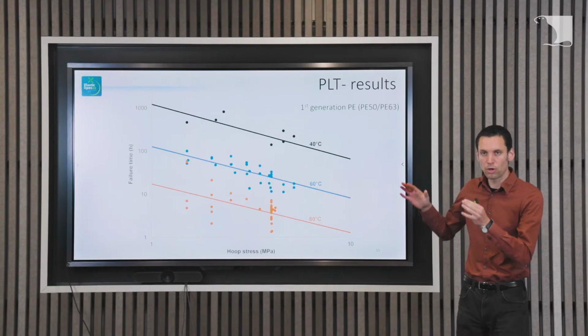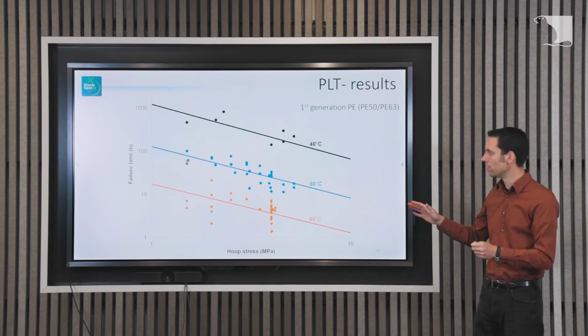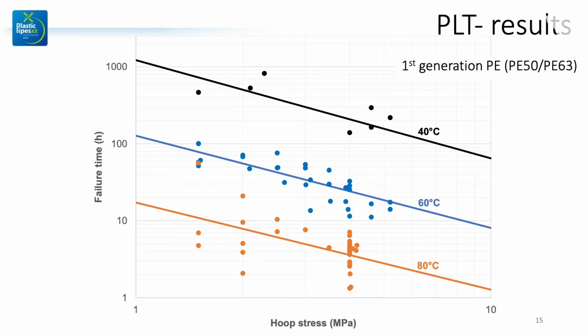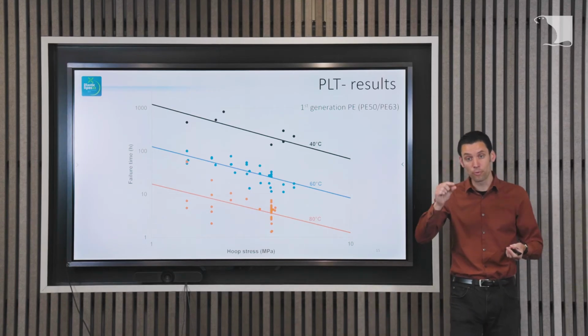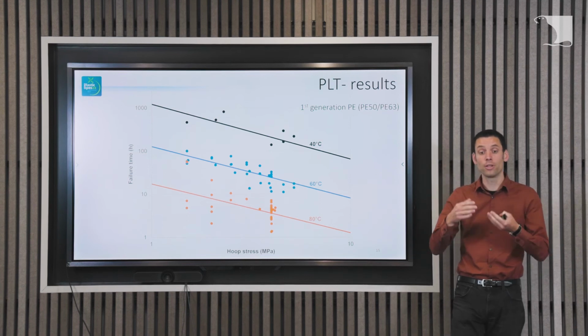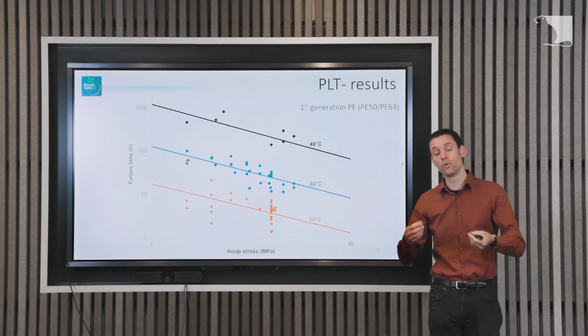We did already quite some tests, especially on the first generation polyethylene that is used in the Netherlands. So that's really the polyethylene pipes that were installed like 50 years ago. We already published it, and these are, well, the latest results. So what do we see here? First of all, on the vertical axis, we see the failure time of these pipes. On the horizontal axis, we see the hoop stress. So the internal pressure actually of those polyethylene pipes, but it's corrected for the wall thickness. Of course, a pipe with a thinner wall will have, under the same pressure, more stress inside the material than a thick wall pipe.